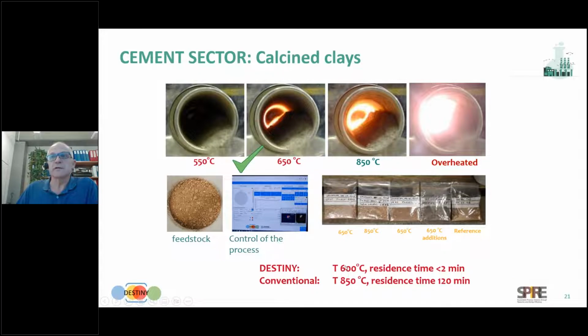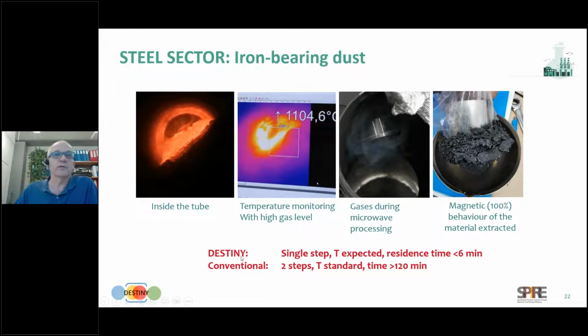The conclusion we can draw from this product, and the advantage, is that with Destiny 600 degrees is good enough, and the residence time is less than 2 minutes, compared with the conventional process at 800 or 850 degrees, with a residence time of around 2 hours. In the steel sector, we can perform the process in a single step, with the reaction and the separation of the metal. And the temperature is as expected, so not a big difference.